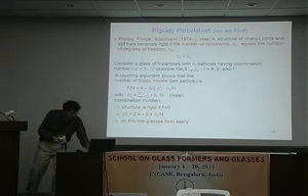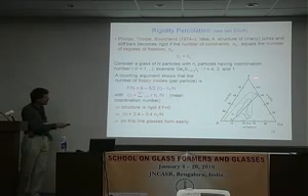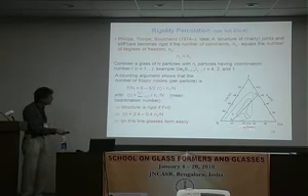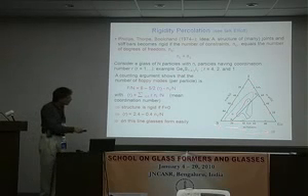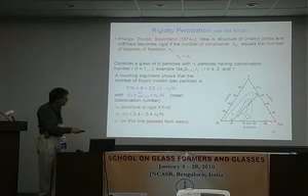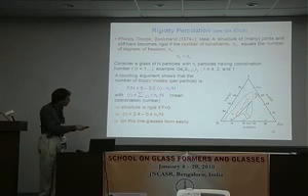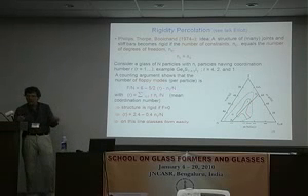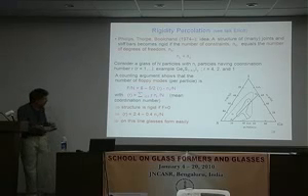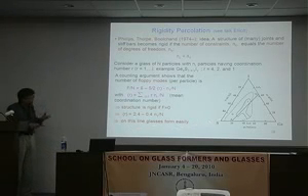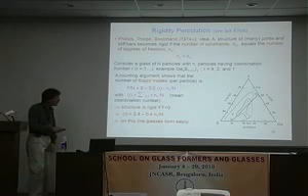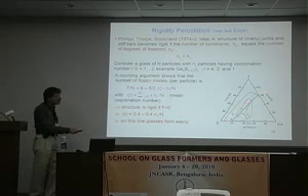And yes, it does. So here, this is a phase diagram of this ternary system. Different compositions, depending on which point you are at. And so zone 1 here, that's the region where you have good glass-forming ability. Okay? That is to say, if you cool the system slowly, it really will form a glass. And the line here, yes?